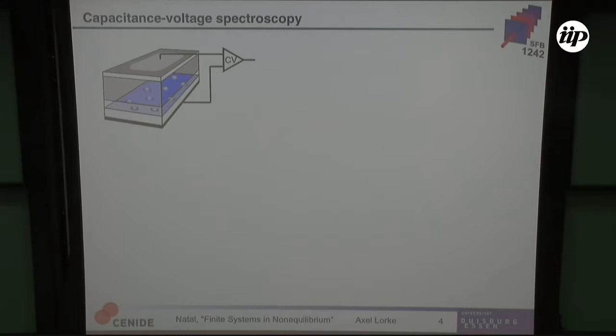So how do we approach the energetics and the dynamics in these quantum dots? We started off a long time ago with capacitance-voltage spectroscopy. So you grow a conducting back contact below the quantum dots, and you put a surface gate electrode on top of the surface, and you measure the capacitance as a function of the voltage. And as you have heard yesterday from Tomasz Nowotny, the AC conductivity is related to the density of states. And you can approach it the way he did it yesterday, or you can think about Thomas-Fermi screening, where also this term e squared times the density of states plays a role.